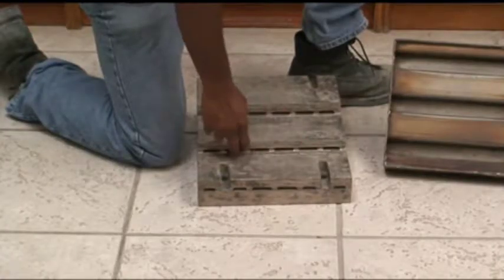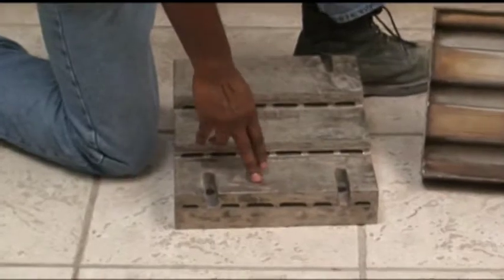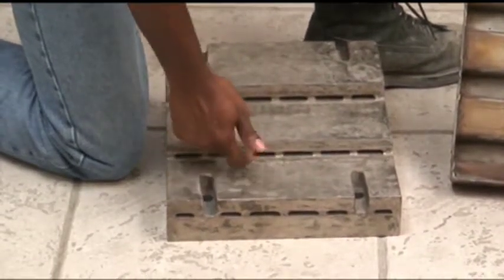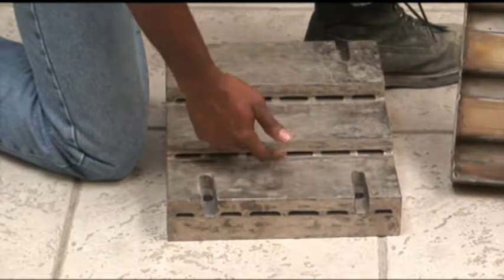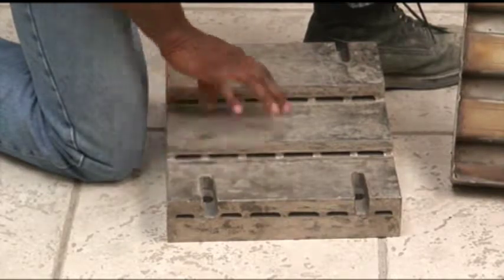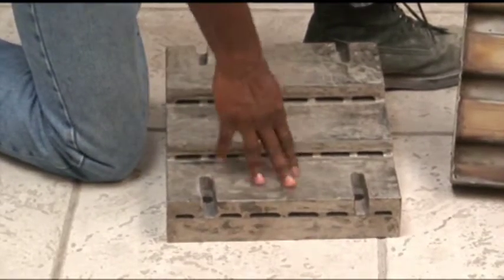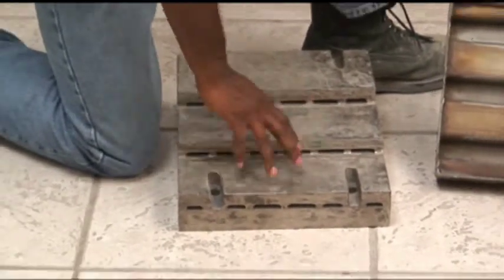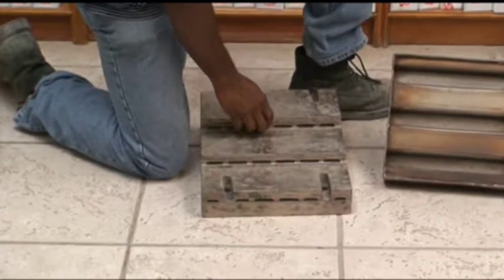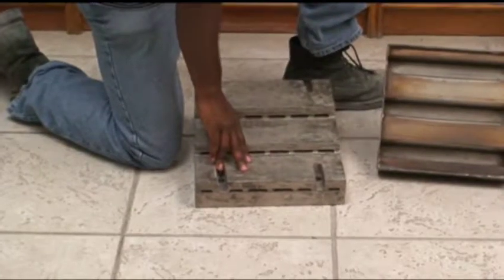In contrast, this grate, the ABC grate, was designed for hot clinker, the surface to be attacked by this hot clinker. This layer of clinker is rapidly removed from this ABC inlet by blasts that come through these holes. These are the blasts from the blasters. These aligned holes allow the clinker to be blasted off the grate plate, thus not allowing this hot clinker to sit here for any length of time so that it might create any damage to the grate itself. It is much more robust, and with this type of step formation, it allows this grate to perform a lot better in comparison to this CIS grate.